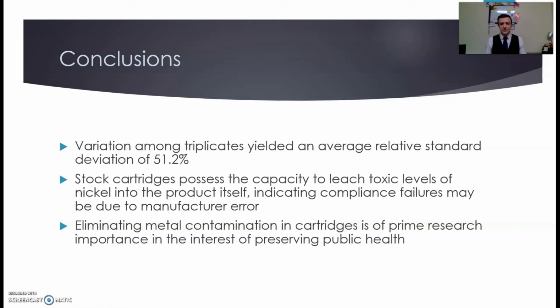Currently, the machinery used to stock these cartridges with cannabis concentrate is constructed of stainless steel. That and the capping process of these cartridges, which is either done through a hydraulic press or a screw-on cap, could very easily flake off parts of the stainless steel into the product and lead to compliance failures. These failures could potentially cost the producer hundreds of thousands of dollars, but this is not just a producer issue.